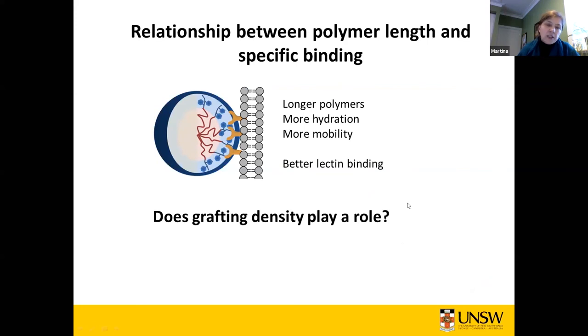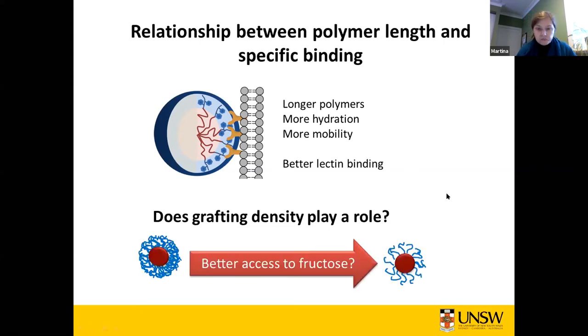So looking at that, we actually said, well, it sort of means that we need to have very long polymers, but we also should have only a few polymers. So we don't want to have this really dense brush. We want to have these polymers nicely flowing around so they can really interact with the receptors on the surface. So that was sort of our hypothesis. We needed to have better access to fructose. If we make a nanoparticle that looks like that, it should work beautifully.